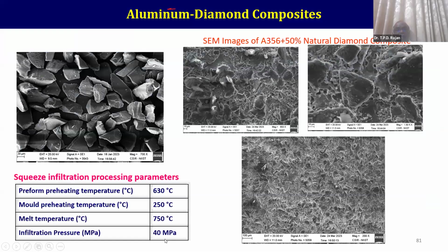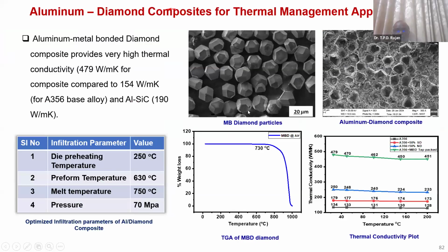So you can see that the annealed one shows very low thermal conductivity in the graphene, the layered structures. Then we thought that we will use diamond, which again has higher thermal conductivity. So we had taken different types of diamond particles, and we infiltrated them, and this is a component. And here, this is a metal bonded diamond which I had used. For this present study, we had taken this A356 alloy, then with synthetic diamond, natural diamond, and metal bonded diamond. And we found that this metal bonded diamond, the interface is very good, and it's a highly crystalline diamond particle, which shows very good thermal conductivity.